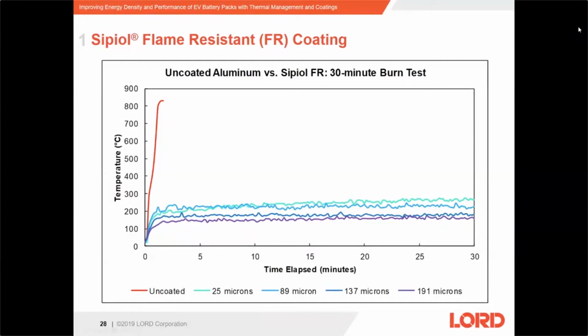Here we have a comparison of uncoated aluminum and Sipiol FR coated aluminum when exposed to a 30-minute burn test, so a test that was 3 times longer than the video that you just saw. As you can see, the temperature of the uncoated aluminum spiked very quickly, reaching over 800 degrees Celsius in about 2 minutes, whereas all of the different thicknesses of the Sipiol FR coating maintain the temperature of the aluminum below 300 degrees Celsius over the entire 30 minutes.